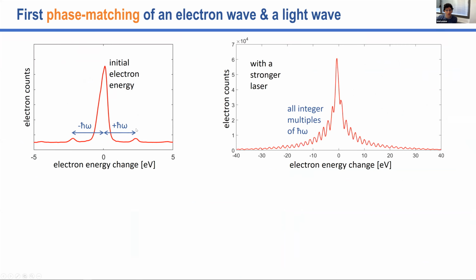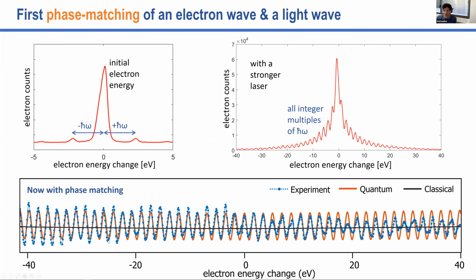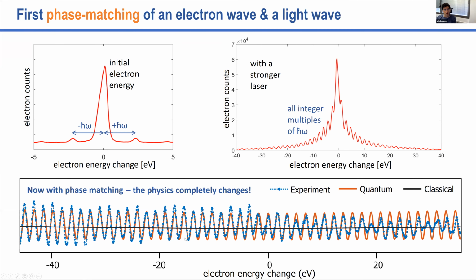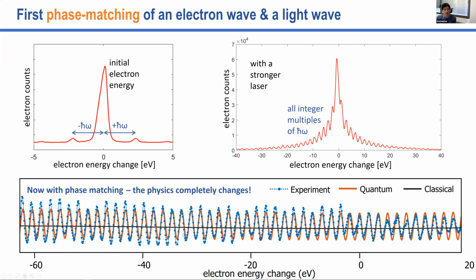When we increase the intensity of the laser, we see multiple peaks, like you see here on the right. So there are multiple peaks on both the gain side and the loss side. And when we match the interaction precisely, and that's really the frontier for our group, we find that the EELS completely changes. You can no longer identify what is the zero loss peak, because it becomes one of many peaks along this plateau of energy peaks that is extremely long and broad. And this is the frontier of extreme interactions of electron and light.